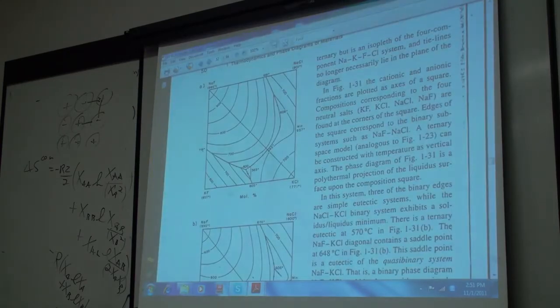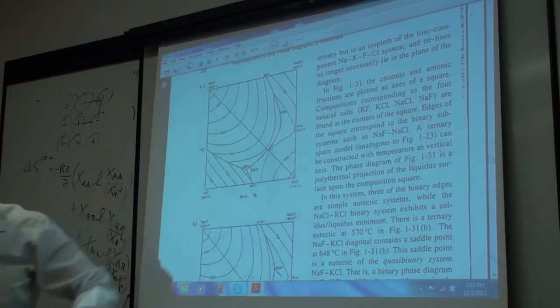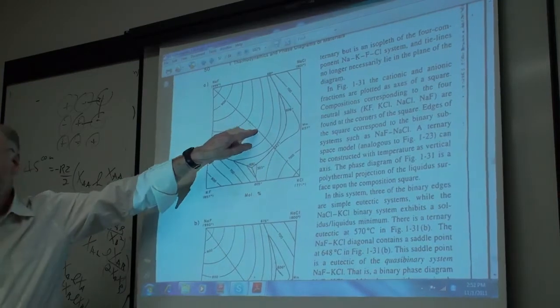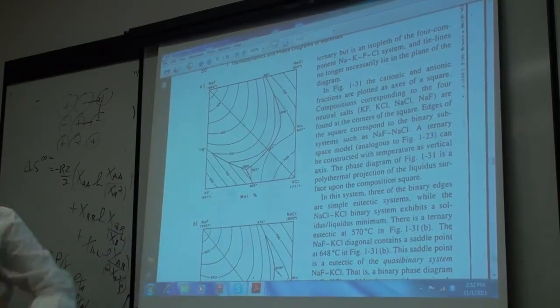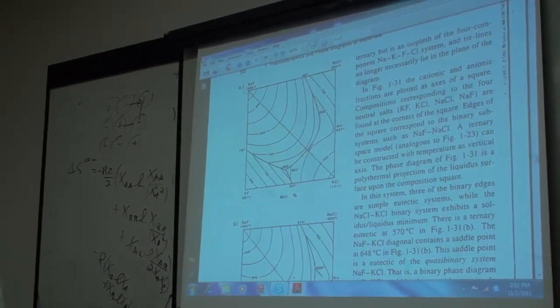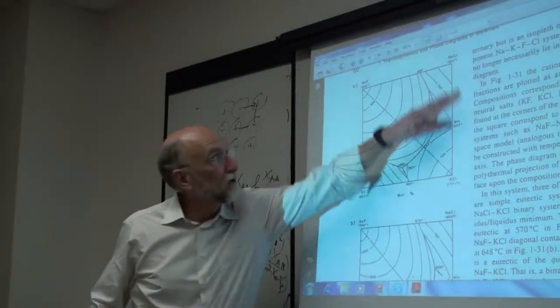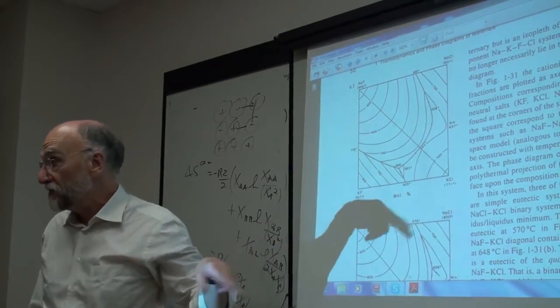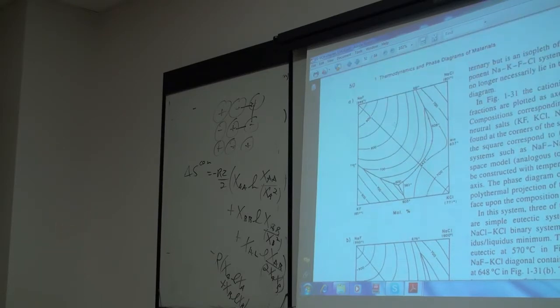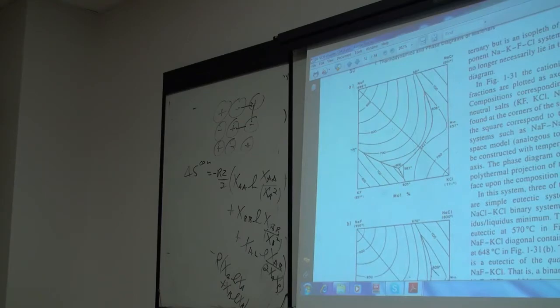So that takes us back to this. That term is negative, so it brings down the miscibility gap. If we didn't include that term, the miscibility gap was too big. Now it brings it down, and it brings it down most in the very center, which is what you want to do. And of course that's a purely reciprocal term. It's the product of all 4 site fractions, so it's 0 all around the edges. It has no effect on the binaries. One of those y's has got to be 0. And when you use that extra term, this is what you get.